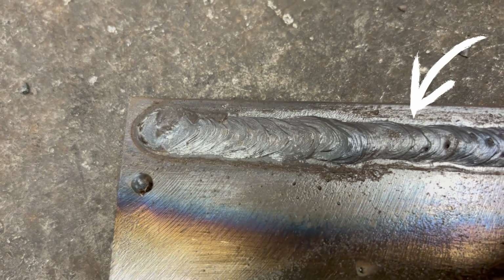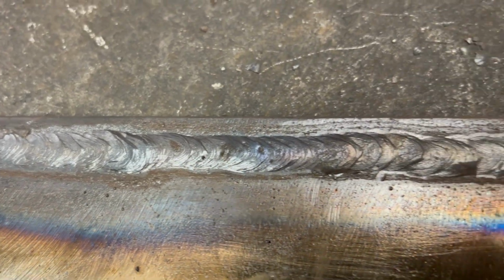Our first error we're going to be looking at is what happens when the welding rod is held too far away from the workpiece. This run shows how it affects the weld appearance. The ripples become uneven and lose their uniformity because we're not maintaining a consistent deposition rate, and it can lead to porosity forming in the bead.